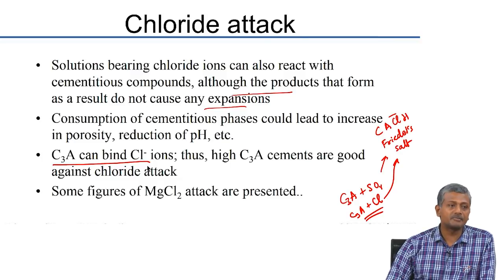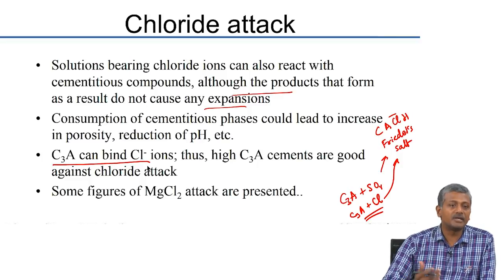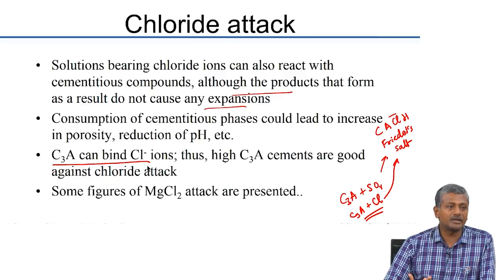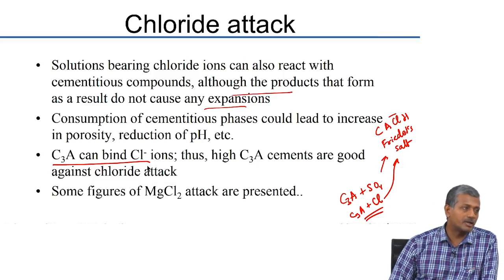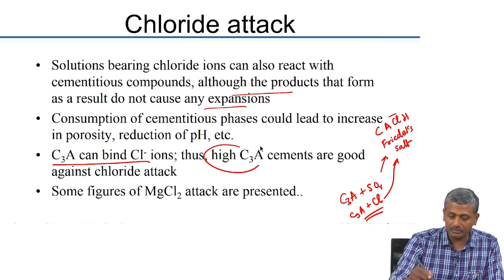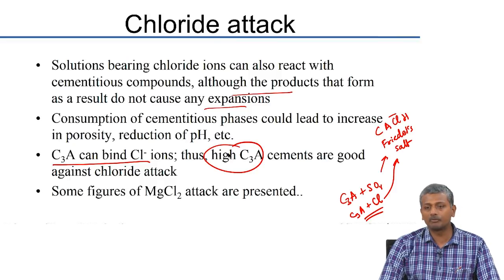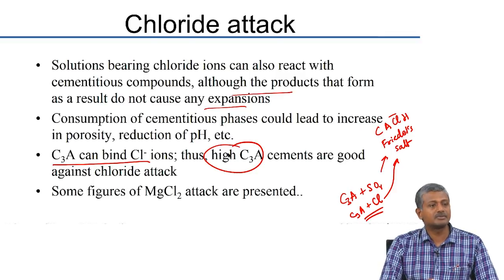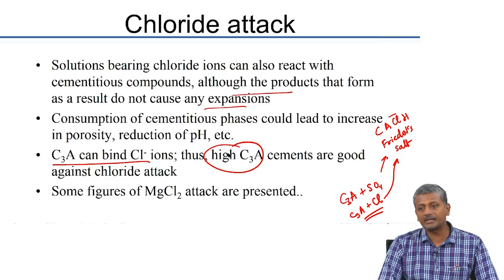This binding mechanism can be improved by substituting cement with mineral additives that have aluminates in them, such as clay and slag, which contribute lots of aluminate that can bind chloride ions into a non-expansive product. When you have cements rich in C3A, you can actually have good performance in chloride attack. This is the opposite of sulphate attack: in sulphate attack we need lower C3A; in chloride attack we need cements with high C3A because that leads to improvement in resistance to corrosion.